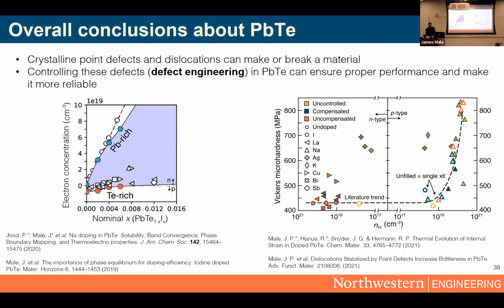So at this point, I kind of have a soft conclusion on all my work that was on lead telluride. So I'm going to summarize these are kind of the main points of my dissertation. So broadly, I would say that crystalline point defects and dislocations are somewhat underappreciated in some regards, but really hold the key to making these materials consistently and making them brittle or ductile. So we actually have these sort of defect engineering strategies now, like changing phase equilibrium or doping on specific sites that can help us tune those properties to improve the material or understand why it's bad.